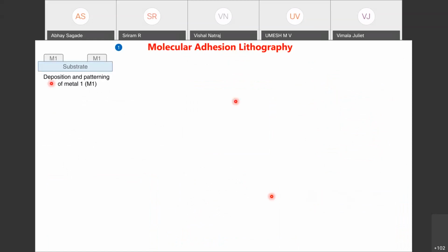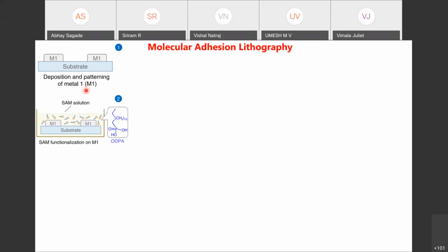To start with, you take an insulating substrate, then pattern one of the metals, written here as metal one. This is done by standard UV photolithography, and then you dip this whole substrate in a particular kind of self-assembled organic monolayer solution. Take a beaker filled with these SAM molecules in one particular solvent, dip the whole substrate inside it and leave it there for a couple of hours, and then only the surface of metal one is occupied with this SAM layer.